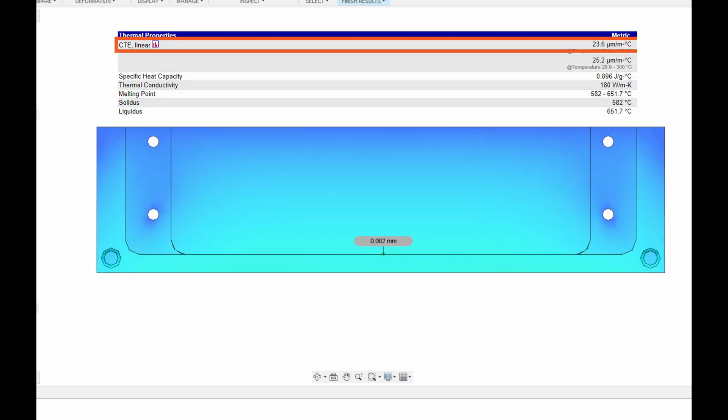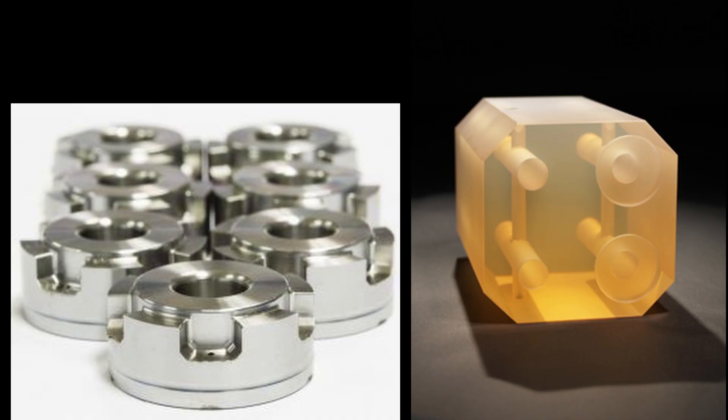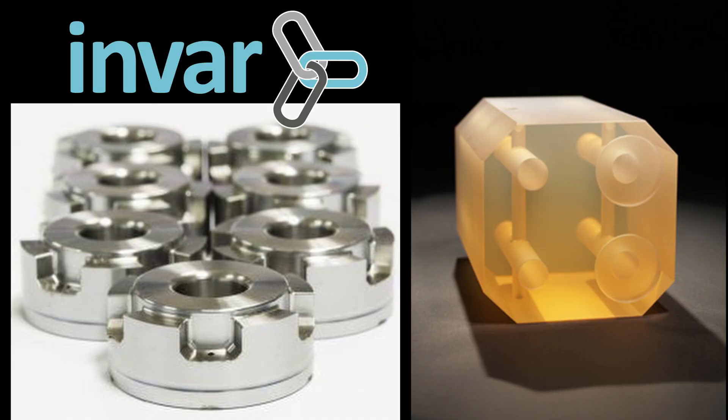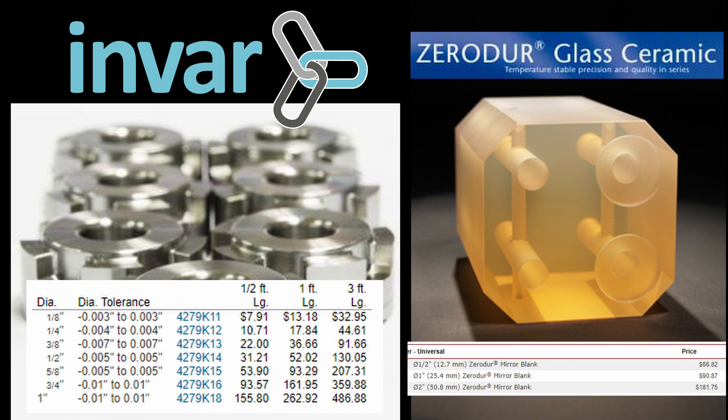So immediately my goal of fixed displacement isn't exactly going to happen. But since the CTE of the aluminum is known to within a couple of ppm, and the path length is relatively short, I'll be able to compensate for it later. There are options out there with very low CTEs like Invar or ZERODUR, but they're quite pricey and difficult to work with, so I'm alright with correcting in post.